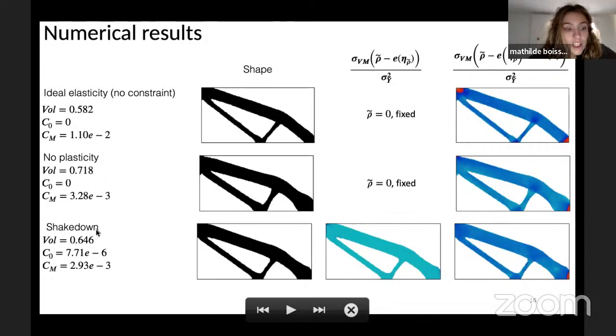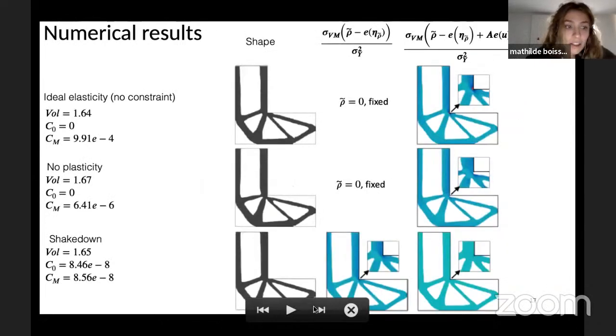And then when we consider shakedown, we see that the volume is actually between the volume for ideal elasticity and the volume when we want to avoid plasticity, which is quite logical because we increased the admissible space by considering shakedown instead of no plasticity. And then we have a residual stress that appears. And we see that both stresses remain in the elastic domain, which is correct. And same kind of results for the L brackets, in which the volume ends up between the volume for ideal elasticity and the volume for no plasticity.